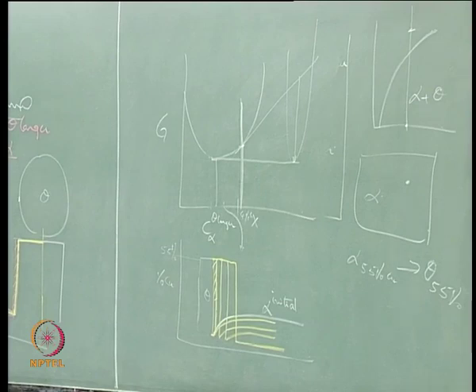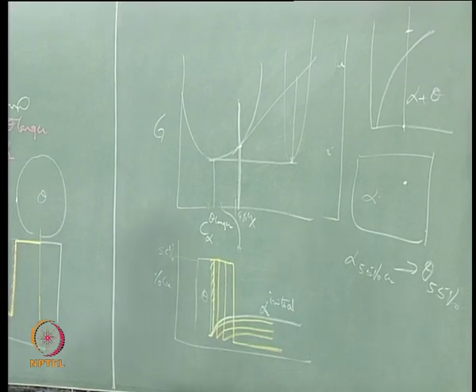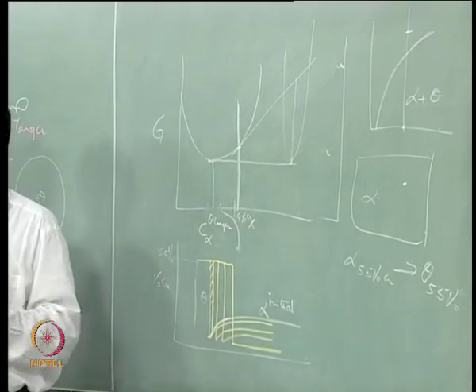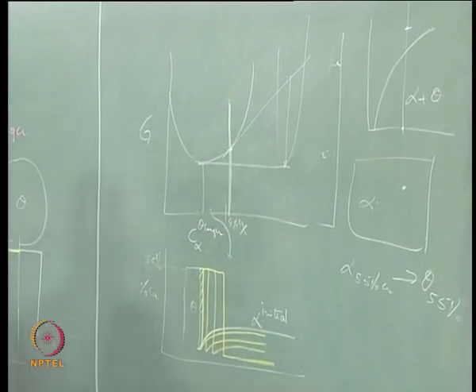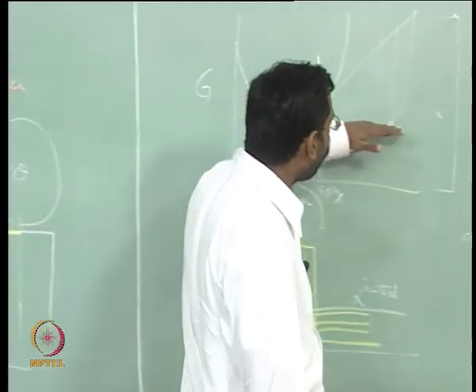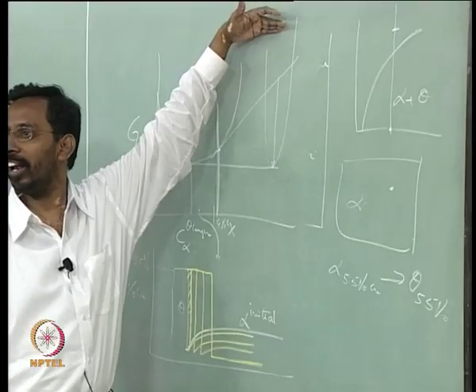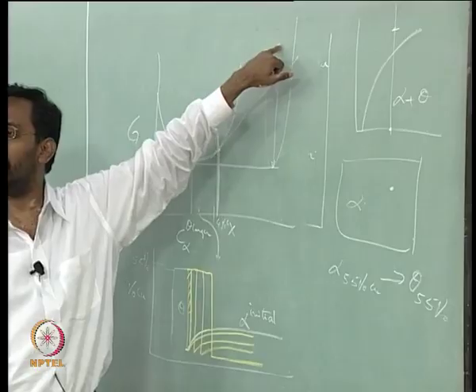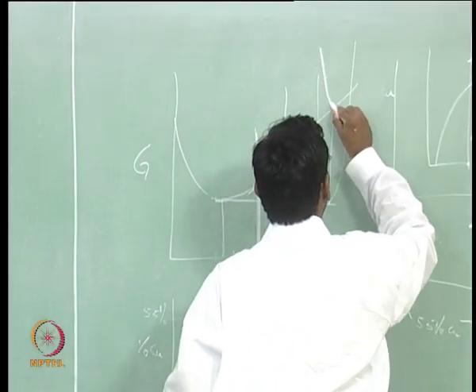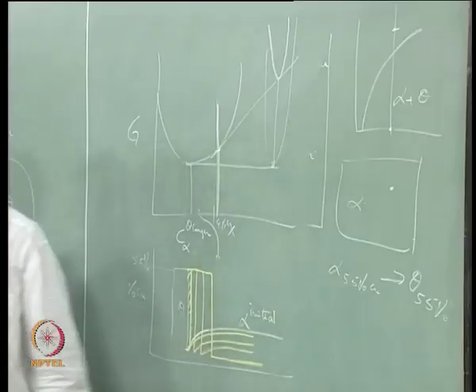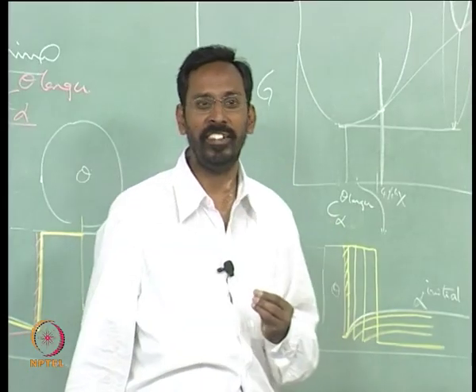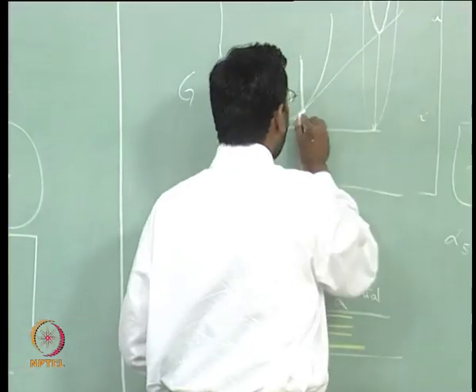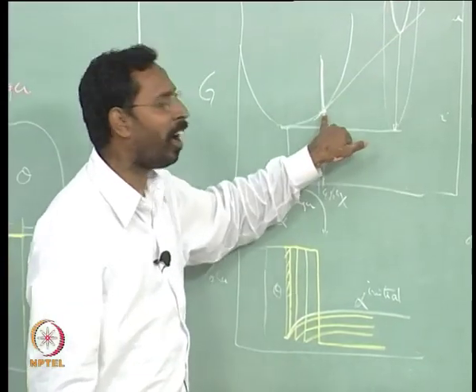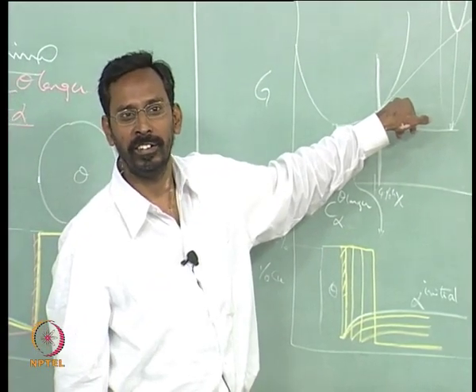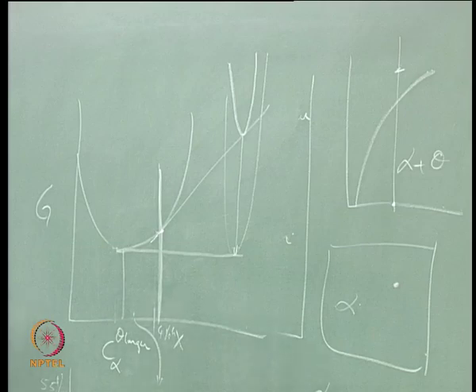And then the free energy should be higher. In principle, you are right, very right. If I consider that the theta is very small, you can draw the free energy curve of theta much higher, and see that the common tangent with that particular theta can be drawn. If this is the theta at the nucleation stage, you can draw a common tangent between that theta and the starting alpha itself. This is assuming that small amount, but this is only at the nucleation event.